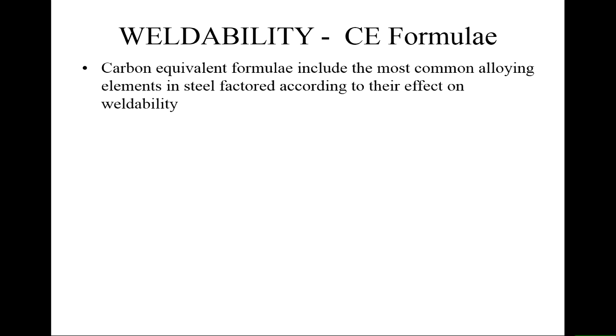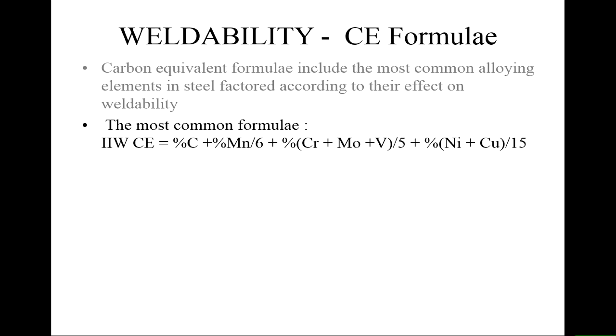So the steel industry did it for developing tools, and the welding industry's done it for developing constructional steels. And so it's a different use of the same ideas. So the International Institute of Welding equation is the most common formula. So the carbon equivalent is the percent of carbon plus the percent of manganese over 6, that was on that diagram, plus the percent of chromium, molybdenum and vanadium over 5, plus the percent of nickel and copper over 15. Those are the main steel alloying elements, and you can see that everything that you do has an effect.